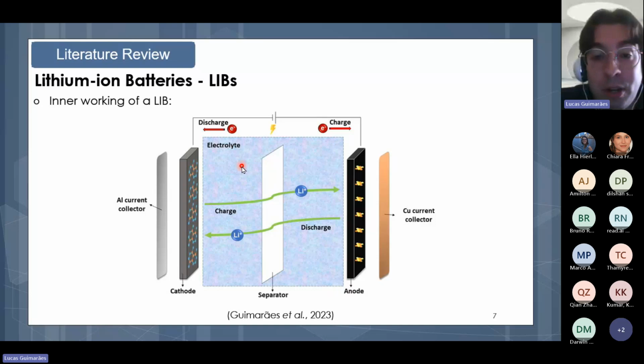And how does it work, for instance, when we are charging the battery? During the charge, lithium ions go from the cathode active material to the anode through the electrolyte. Thanks to the electrolyte, this movement of the lithium ion is possible, and that is how the battery works during the charge. During the discharge, when you're using the battery, the process is the other way around.